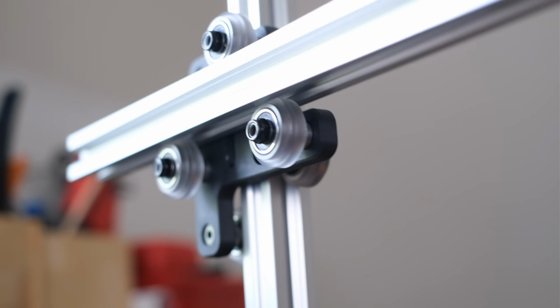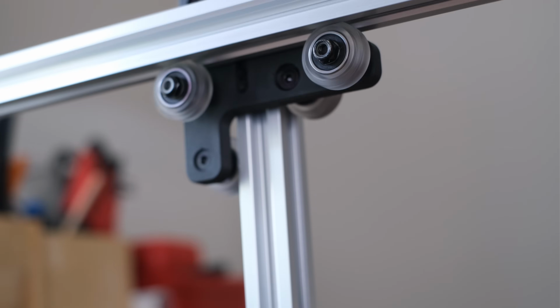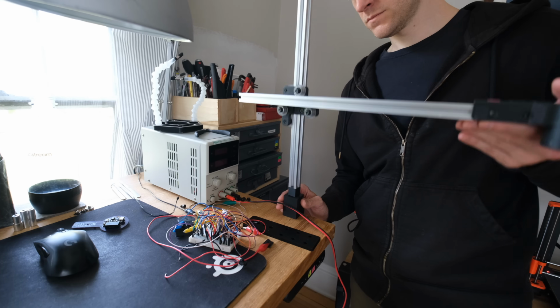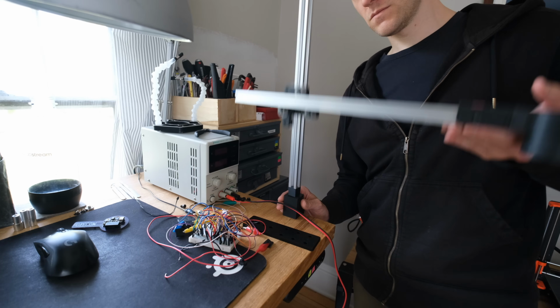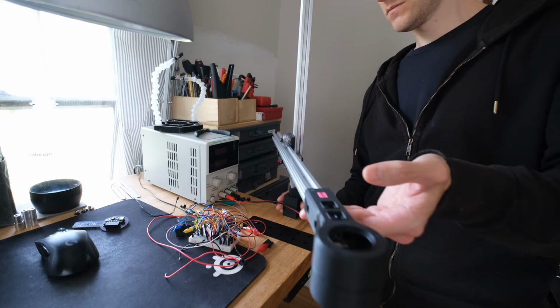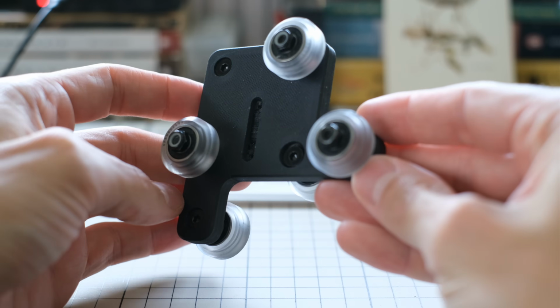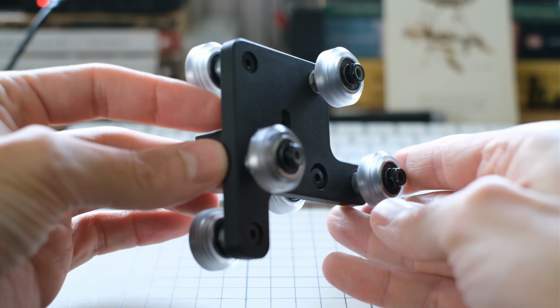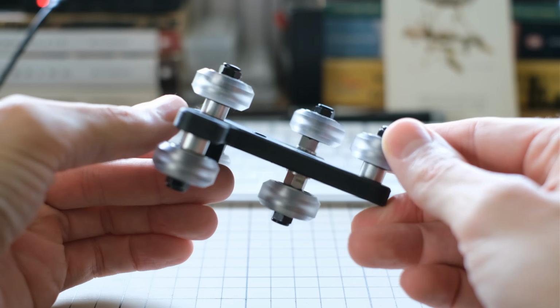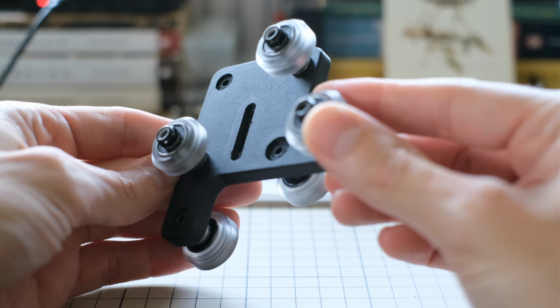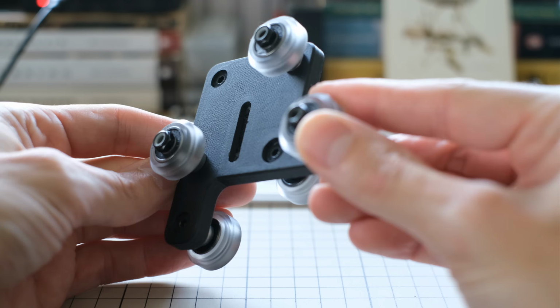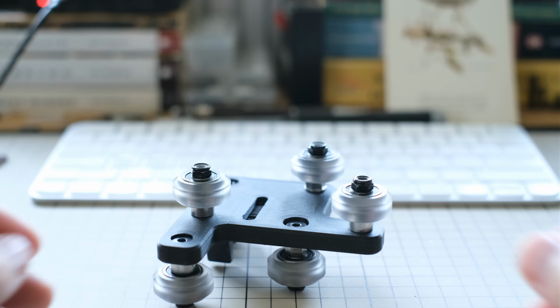I already printed a carriage with this just to feel it, and it feels really good. The stiffness adds this level of precision and responsiveness when moving the lamp around. So while it's never going to be as good as the aluminum carriage, it's a really good alternative at $1.70 for the part. Since this prints a lot like PETG, it prints really well on the satin PEI sheets, and so the print surface has this really nice finish, and it looks even better than the old carriage while blending in with all the other black parts on the OpenTask Lite. So I'm going to go forward with the PET carbon fiber blend.